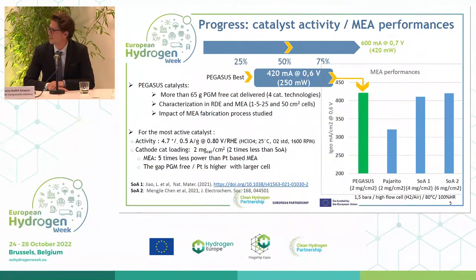And for the most active catalyst, we also compared the activity that we measured in 3 electrode setups, and it was good results, very comparable with state of the art reported in literature. We also made those MEAs with 2 milligram of PGM-free catalyst per square centimeter. It's around 2 times less than what is proposed in the literature. So if you are focused on that perspective, we can say that with 2 times less catalyst, we've got the same activity for the MEA, comparing with data publicly available in literature.